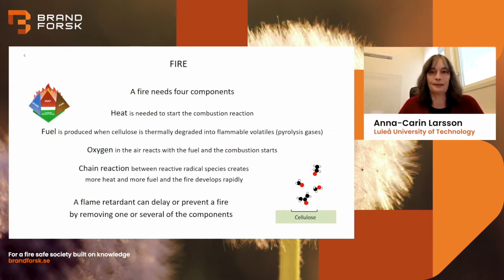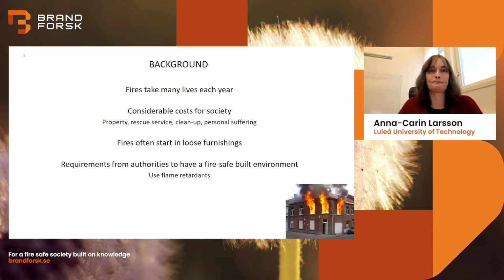So those fragments, the pyrolysis gases that form, they are radical species which have unpaired electrons. So they are very reactive, quickly want to react with other species, and then new radicals form. So we get the chain reaction where more heat and fuel is formed and the fire develops rapidly. So a flame retardant can delay or prevent the fire by removing one or several of those components.